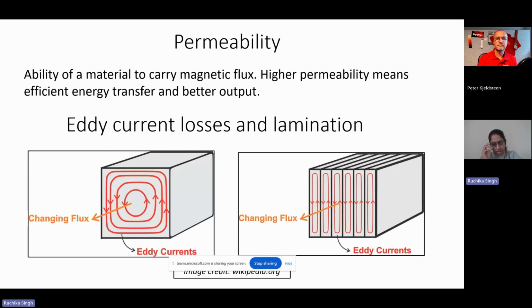And eddy currents, I also talked about: when you have this change in magnetic field in the material, you have eddy currents induced in the material. If you see the picture on the left side, this is a very simple comparison I got from the internet. You have a thick block of material, and you see the path of the eddy currents is quite long. On the right side, the block is now cut into small sheets. Why you do that is you're trying to make this eddy current loop smaller. When you make these loops smaller, you reduce the eddy current losses. You're making the path shorter, and so you reduce the eddy current losses.